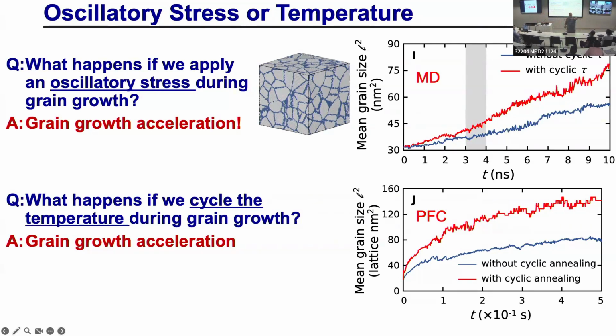Well, the way you cheat is very simple. When you hold it at a temperature, say 400, and I go plus or minus 50 degrees, since at 500 it goes much, much faster than at 450. If you do it at 400, it goes slower. But the net effect is you're going fast. You have the same amount of time where you're going fast and the same amount of time you're going slow, but it doesn't average the same. So I can actually take those two curves and do this correctly. And I don't have it here, but you can show that this curve is way above what you would expect from just the average of the hot and cold.